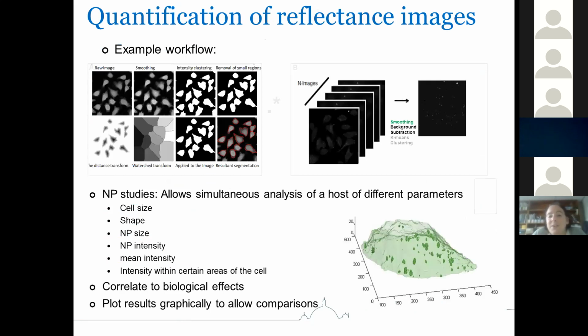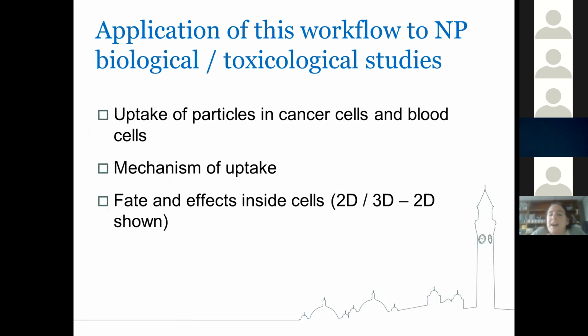So this works really nicely for quantification of the reflectance images, and by adding the fluorescence, as I said, we can track in parallel both the nanoparticle quantification and the cellular quantification. So we can look at things like the impact of nanoparticle concentration on cell size, on cell shape, on the nanoparticle size. So we can also look at things like the potential for dissolution of particles once they've been internalized. We can look at nanoparticle intensity, which correlates with particle number and particle size, and the intensity then within certain areas of the cell. So we can correlate the nanoparticle uptake with biological effects and plot it graphically to allow different comparisons.